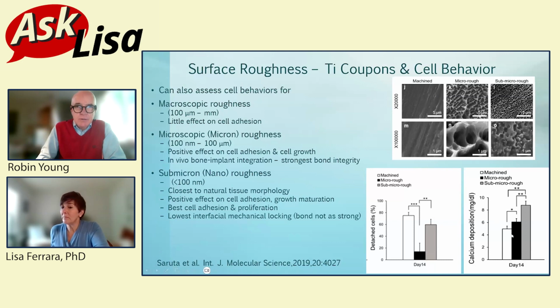Okay. And compared to the machined surface, which, as you can see, is a roughened groove from the equipment basically, it had a moderate calcium deposition, better than machined, obviously. When you get to nano roughness, less than 100 nanometers, that's closer to the tissue morphology from a molecular perspective. It doesn't have a very strong interfacial mechanical locking bond, as you can see here. It's less than the machined, but much greater detached cells than that of the micro. But what you do see here is you have better calcium deposition. So you're getting that cell adhesion and proliferation here. You just don't have as strong a cell adhesion bond as the micro.